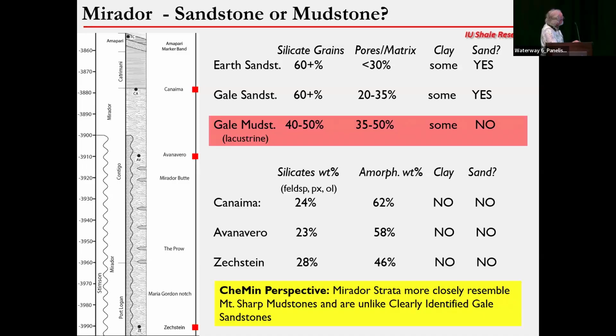If you then look at the Mirador samples, Zechstein, Avanavero, Canaima, you see relatively low contents of silicate minerals that are the grain formers typically in a sandstone. And then you have lots of amorphous stuff, no clays, and no visible sand. From a chemical perspective, the Mirador strata more closely resemble a Mount Sharp mudstone and are unlike clearly identified Gale sandstones. Okay.